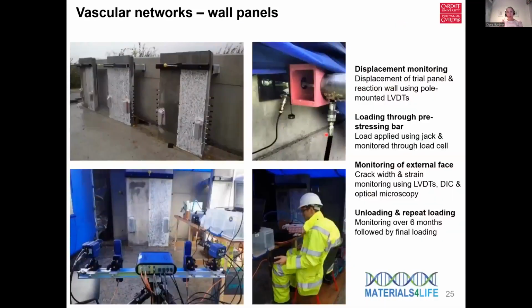We used a series of displacement monitoring techniques. We actually loaded the walls through a pre-stressing bar on the back and essentially created a tension crack across the front of the specimens here. We looked at the external face and used a series of LVDTs, digital image correlation, which is why you see these speckled patterns, and optical microscopy to look at the propagation of those cracks.